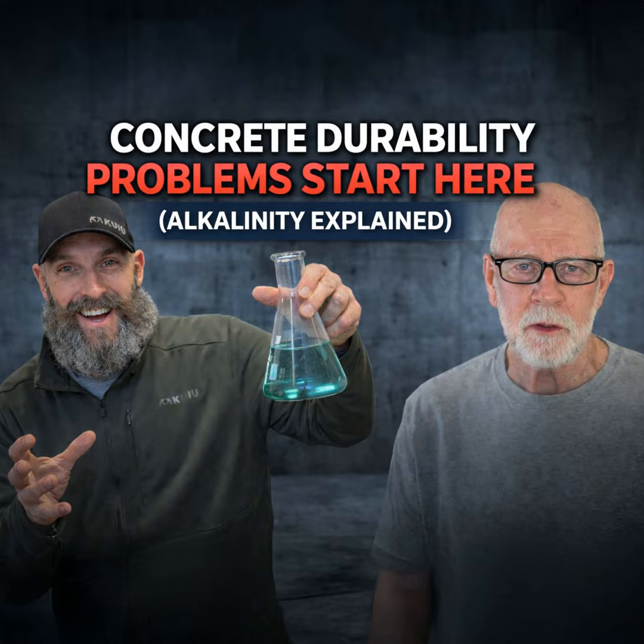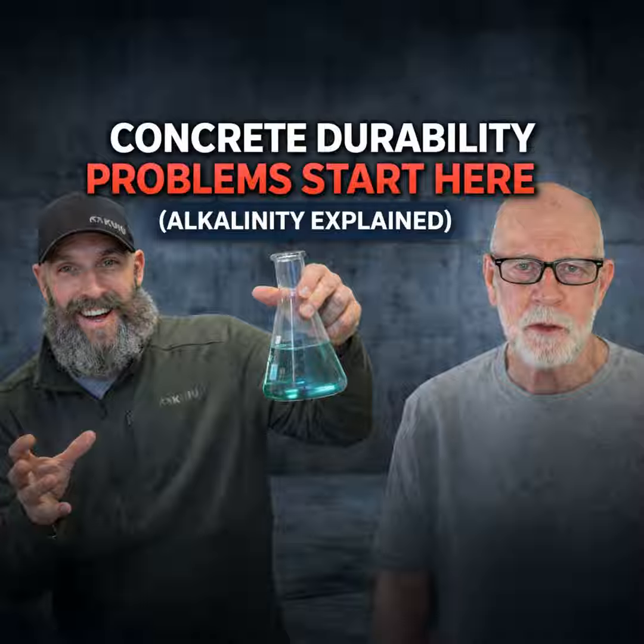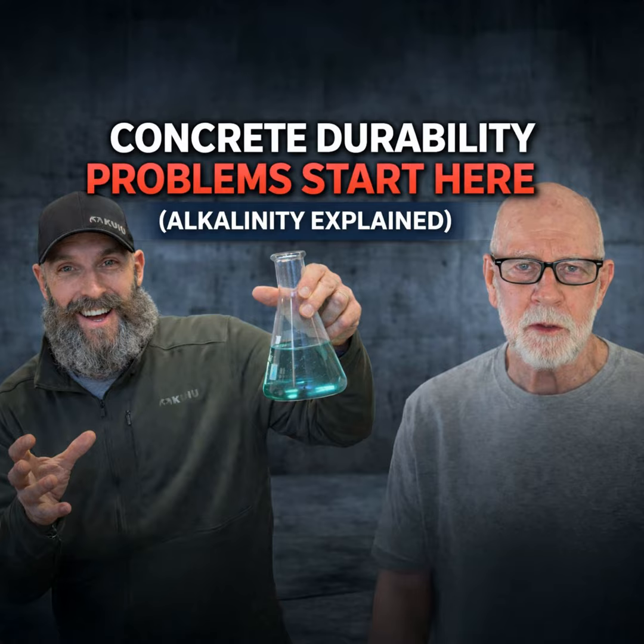So I experimented with this on a case I was brought in where I suspected there was a sodium alkaline salt in the concrete, and where it was severely damaged, I did what I call a relative alkalinity test, where I did the normal pH test, but what I did is I put a ring of plumber's putty down and 0.5 milliliter of deionized water. Then I put the pH strip in, and the area of no damage, moderate damage, and severe damage all measured around 11, but the severe damage was up around 12.